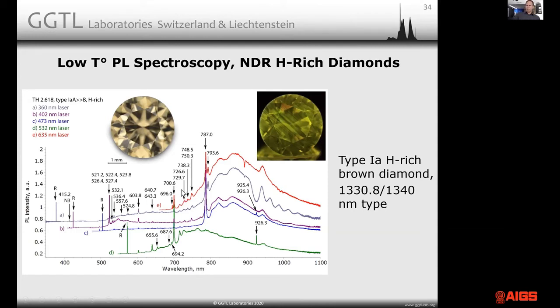It's quite speculative, but it seems very likely that absorption spectra of this type of hydrogen-rich diamond is related to a nickel defect. Often you hear hydrogen-related color, but I highly doubt that hydrogen causes UV visible absorption in this range. It might be a defect that involves all of the above, nitrogen, nickel, and hydrogen, but certainly not hydrogen alone.